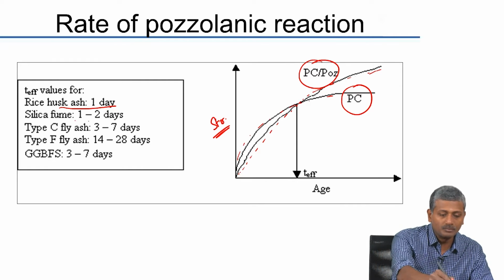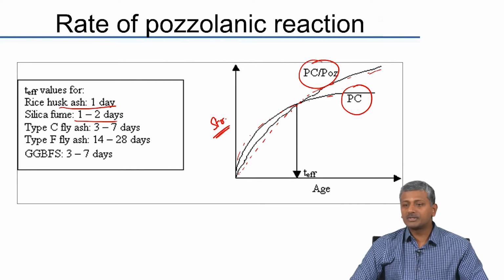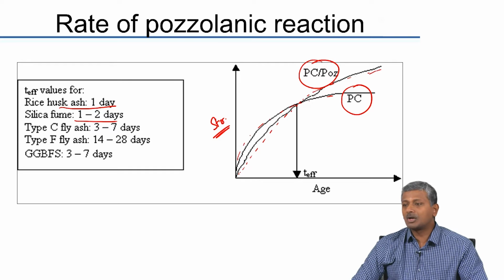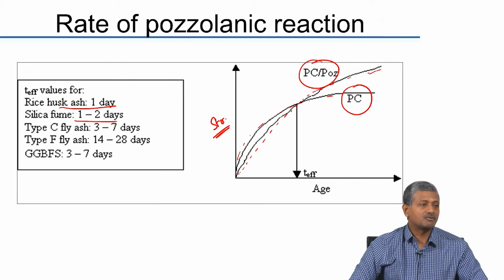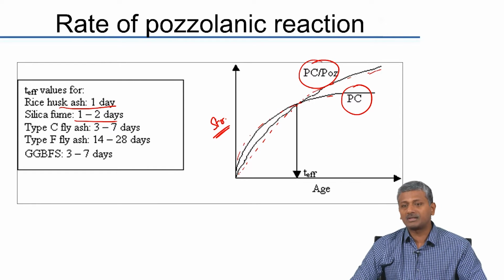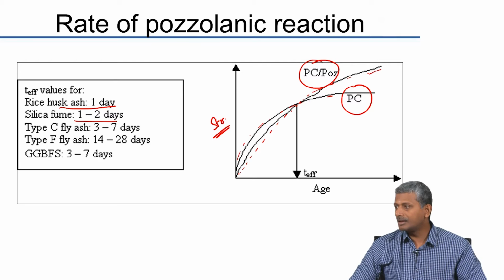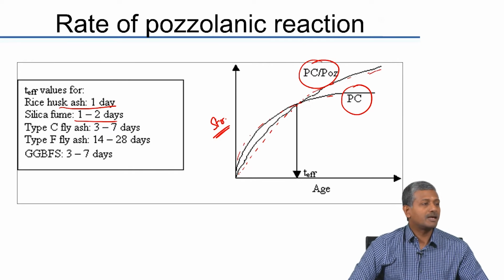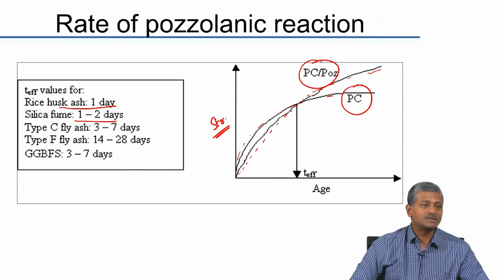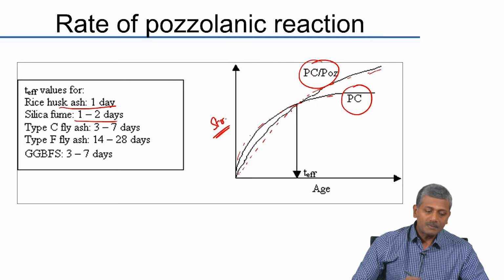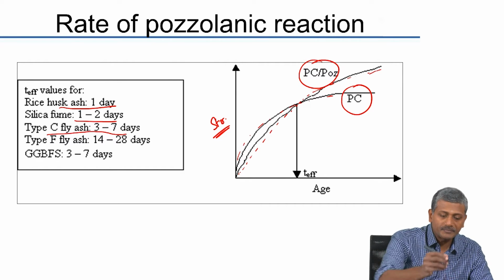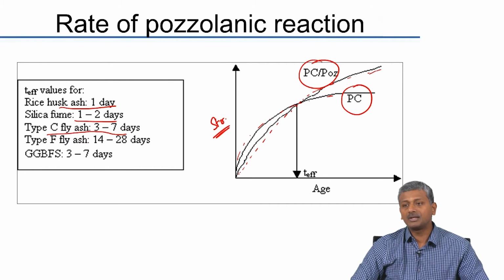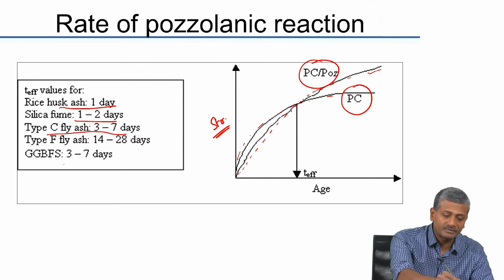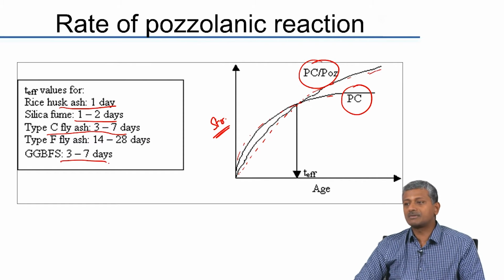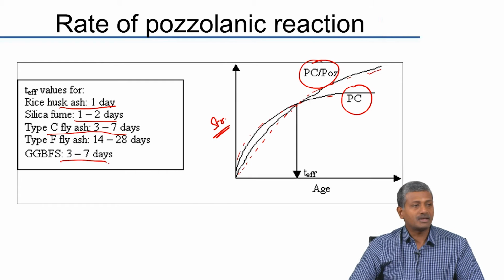Whereas, with silica fume you may still be able to do this at 1 day itself. At 1 day itself you may not have any difference between the Portland cement mix and silica fume mix, and ultimately you will get a much better strength development with silica fume, because again the particle filling characteristics of silica fume are much better than that of cement. Okay. Type C fly ash, which is the high calcium fly ash, takes about 3 to 7 days to attain the same level of strength development as Portland cement, and if you have a slag based system, again you take about 3 to 7 days to achieve the same level of strength as the Portland cement system.